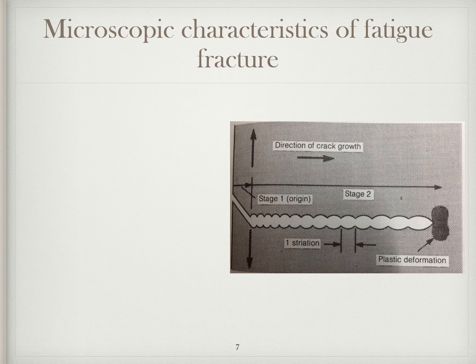However, each time the crack is opened by a tensile stress of sufficient magnitude, the crack tip deforms plastically, slightly blunting the tip on a microscopic scale, which then causes the fracture to advance, creating a tiny ridge or striation on each of the mating fracture surfaces. This is shown schematically in the adjoining figure. So here in the figure, the curved lines at the top represent the ridges on the upper mating surface, and the lower curved lines represent the ridges on the lower mating surface.